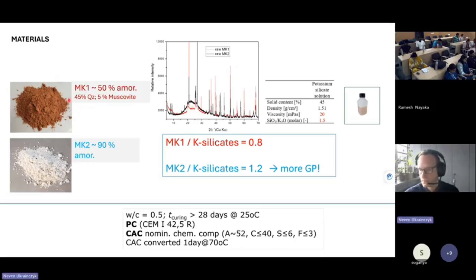With this clay we had very good properties. So we compare this with Portland cement and calcium aluminate cements. I will not go into all the details. Of course we are using potassium silicates, not sodium, because potassium is better, although it's a bit more expensive, but it gives better rheology and also less leaching.